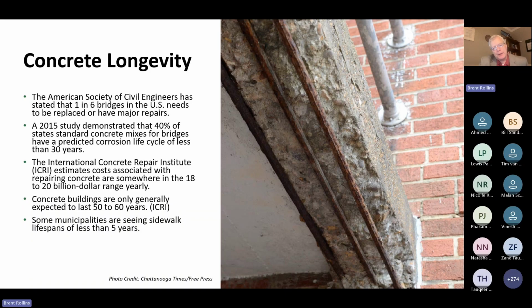What happened here is at the bottom of this beam, the reinforcing steel began corroding, and the reaction products of reinforcing steel corrosion take up at least 4 or 5 times the volume of the original steel. So as that steel begins to corrode, it grows. And when it grows, it exerts tensile stresses on the concrete that eventually blows the face off the concrete, something that we refer to as a spall, or a reinforcing steel delamination, or cover concrete delamination, etc. So that's the key function of what permeability can do to reinforced concrete.